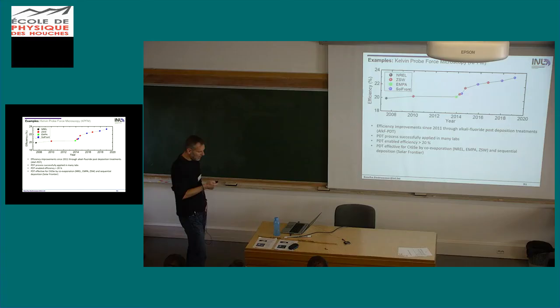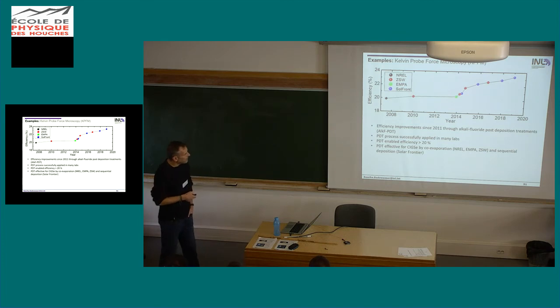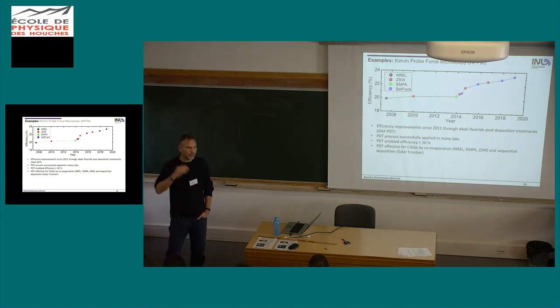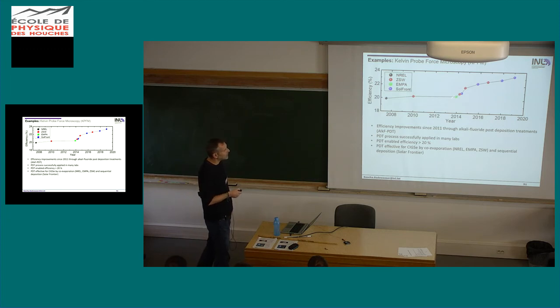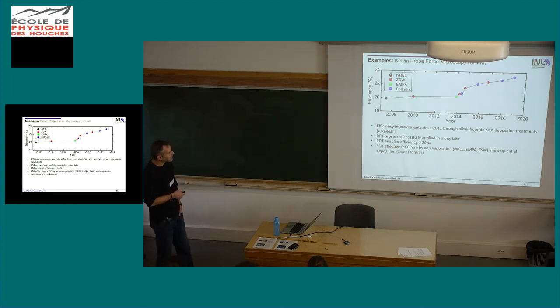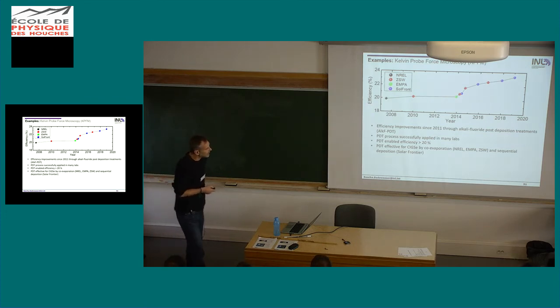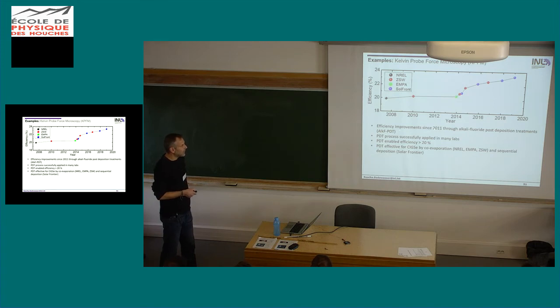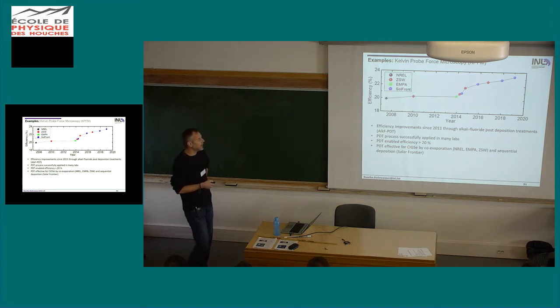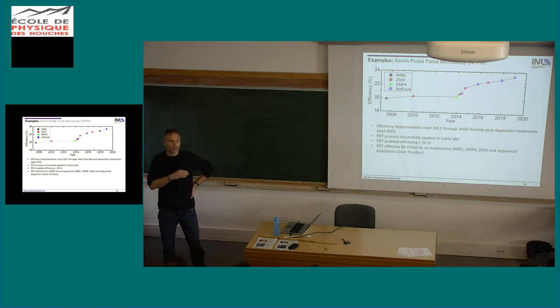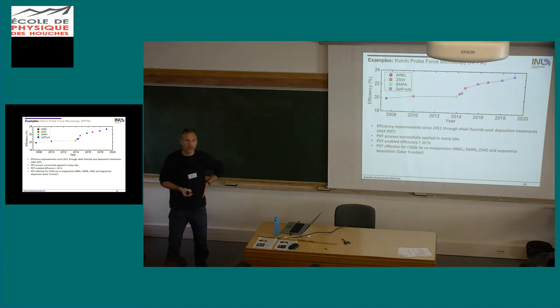Now, a more up-to-date example. We also heard yesterday that there were technology developments which lead to jumps in the efficiency. So this is the efficiency of CIGS over time, only a part of this big chart with all the other photovoltaic materials. And in 2011, more or less at the same time, ZSW and EMPA introduced alkali fluoride post-deposition treatments. Actually, EMPA developed this for sodium because they used flexible substrates which don't provide sodium as the soda lime glass does. So they had to supply sodium after growing their material.